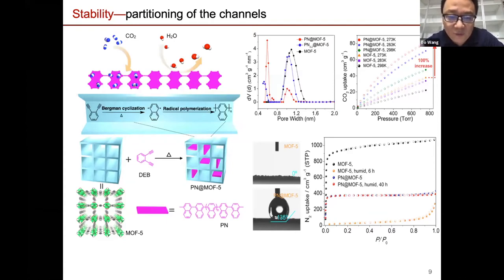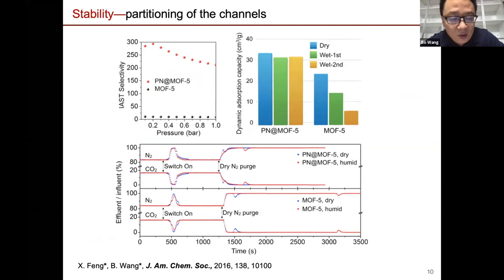And when you cut the pore in half, you fully utilize the inner space and can nicely bond to carbon dioxide, but at the same time, it makes the whole structure hydrophobic, all the way from hydrophilic to hydrophobic. So water cannot enter the pore easily. In that case, we mimic smokestack gas, nitrogen and carbon dioxide saturated with water. Without the polymer inside, as you can see, it will be really hard to purge, to dry up the column. But with the polymer inside, eventually you can purge the MOF5 very easily. So it makes it more useful in these separation processes.